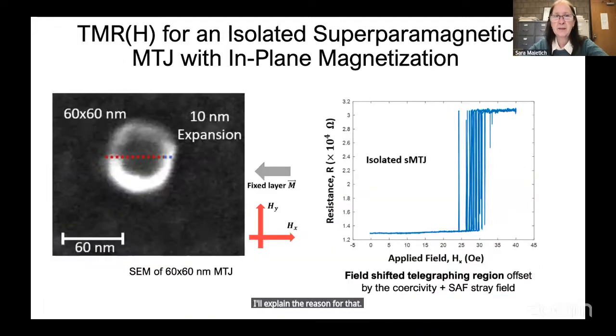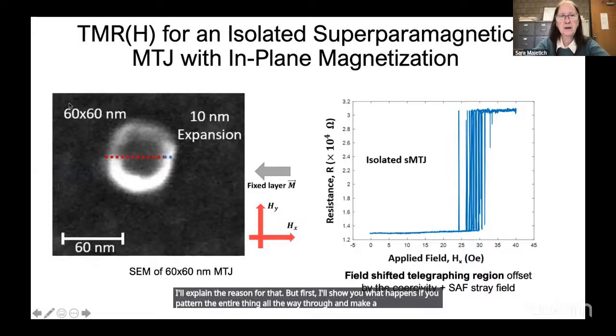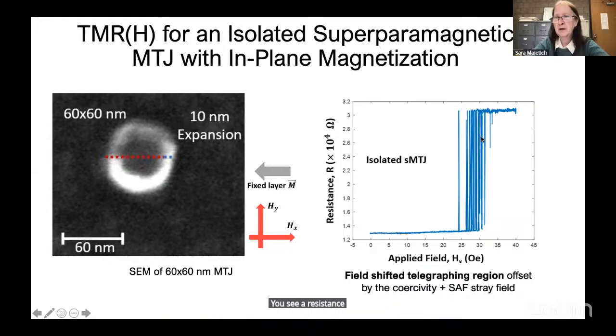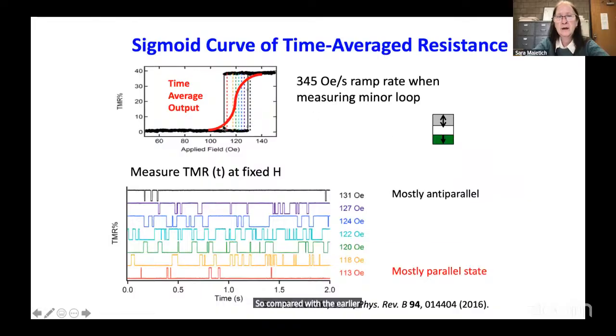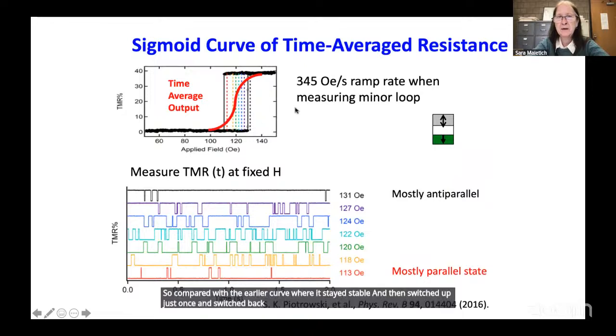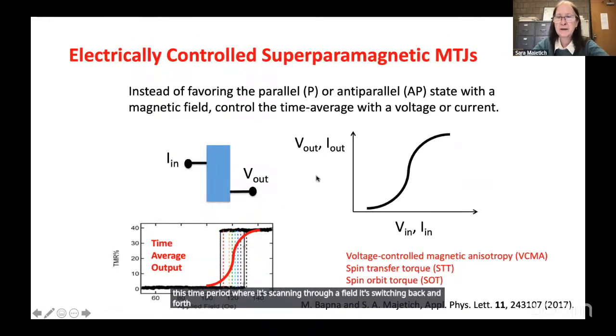But first, I'll show you what happens if you pattern the entire thing all the way through and make a 60 nanometer circular tunnel junction. You see a resistance versus applied field curve that's showing some telegraphing as we scan. So compared with the earlier curve where it stayed stable and then switched up just once and switched back, here the device is switching so fast that over this time period where it's scanning through a field, it's switching back and forth, and you're seeing that in real time.